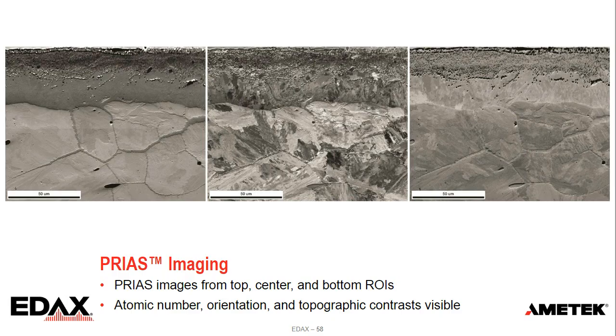So you can see on the left, we're getting atomic number contrast. In the middle, we get more orientation contrast. On the right, we get more of a topographical contrast. That's, again, just selecting from the top, center, and bottom of your EBSD detector to monitor the signal in those regions to create those images. So we get some nice just pictures of the microstructure with PRIAS.